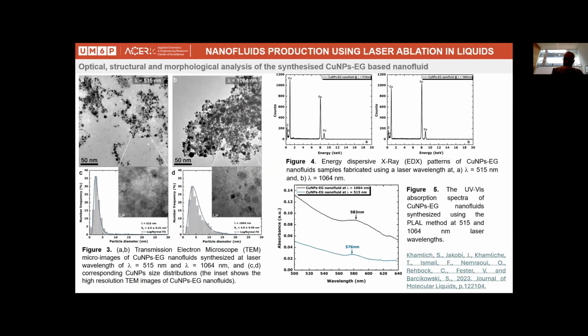So of course, making these nanoparticles, one should really analyze and characterize them. We cannot say we are making nanoparticles inside a liquid without knowing what is there. So here, copper nanoparticles produced in ethylene glycol using these lasers, doing energy dispersive X-ray, it shows that the copper is pure. Of course, if you produce copper in water, you will have an oxide. Here, it is in ethylene glycol. We didn't really find any oxide of copper there.